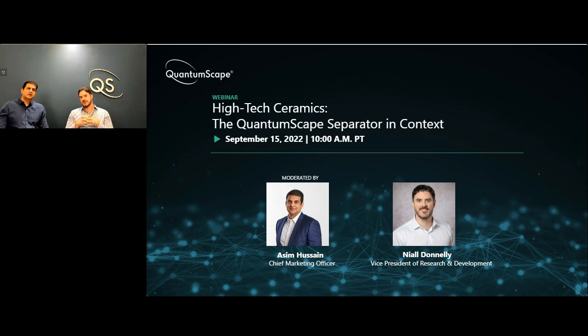Right. And along those same lines, one of the key aspects, I think we've talked about, is cathode flexibility. What is the property of the separator that allows us to have that flexibility in terms of different chemistries on the cathode side? Yeah. So the unique innovation for QuantumScape has been the separator itself. And the separator is great because that makes it compatible with a lot of different cathode chemistries. We can really put in a whole range of the common cathode chemistries that you see in lithium ion technology today: NMC, NCA, LFP. It really doesn't matter. We can substitute any cathode material there that we want, and combine that with our separator and have that as the host to store the discharging lithium. So we've demonstrated compatibility with these different cathode types.